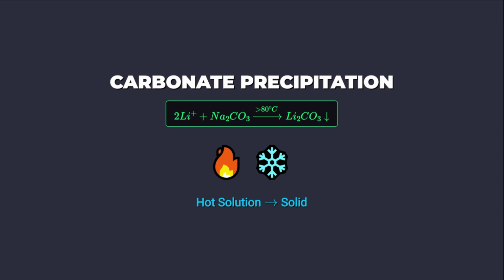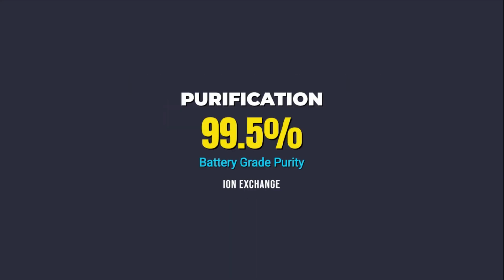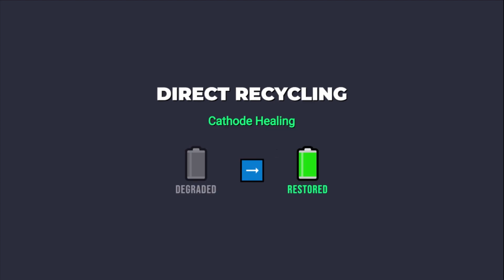Precipitation as lithium carbonate requires the addition of sodium carbonate and careful control of temperature, usually above 80 degrees Celsius, to maximize yield. Achieving battery-grade purity, typically 99.5% or higher, often necessitates further purification steps, such as ion exchange, to remove residual sodium or calcium contaminants.